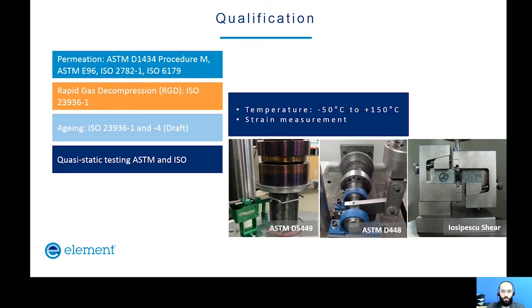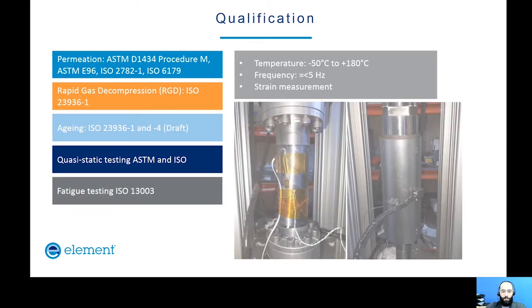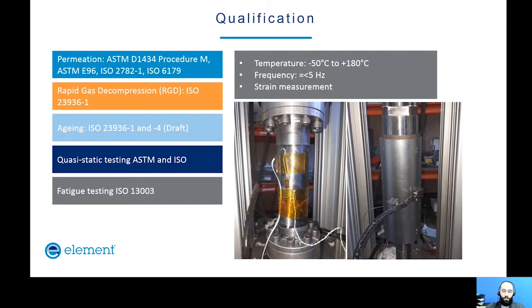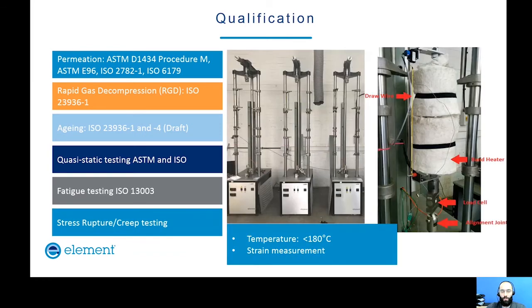So when we test the material at different temperatures, we have to make sure that we do the strain measurement at the same time. These are normally qualified by quasi-static testing on the pipes. There are several different standards that can be used, from ASTM to ISO standards to DIN standards. And then again, very important, the product always goes through different load cycles in the field. So the effect of the cyclic load on the mechanical integrity of the part is of importance. And then the temperature plays a role in these tests. And after that, we move to the effect of the stress rupture or creep, which means the static load that is applied on the product over time will have some effect on the mechanical integrity of the material or the product.